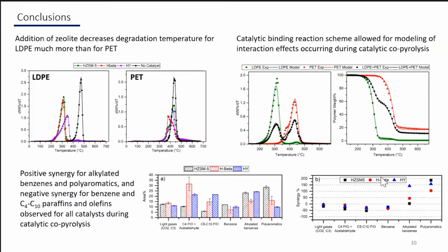Yeah, so that's a very great question, and definitely something that we have been thinking about trying to explain. So we see that for the PET, there's a slight decrease in the degradation temperature, but it's not nearly to the magnitude for the LDPE. And what we are thinking is occurring is that the PET polymer structure is much larger than the LDPE. So we are thinking that the PET may have a harder time entering the pores of these catalysts to enhance the degradation. One thing that we do notice is that the H beta had the highest degradation for the PET, and our H beta also had the highest external surface area. So this leads us to believe that maybe the PET is degrading via the external acid sites rather than the internal acid sites of these zeolites, but that's something that we want to investigate further.